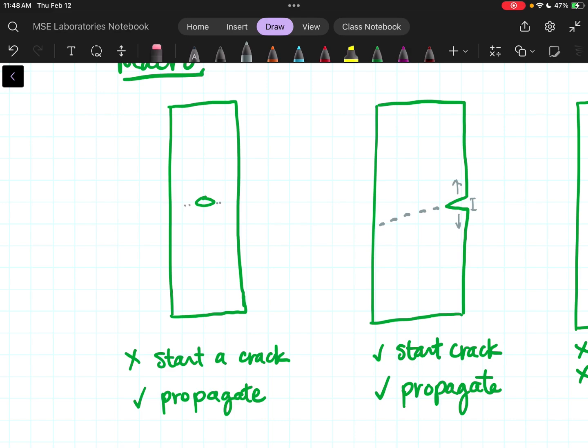The crack may start on the edges of this bubble, but more likely the crack is going to have to start along the edge somewhere. Edges tend to be where cracks start, although they can start from the center sometimes. Which means that we don't have a clear path for where this crack is going to start. But once it does start, if it happens to intersect with this bubble, so let's say my crack meets the corner of the bubble, it now creates an external defect, in quotes, by the crack reaching the bubble.